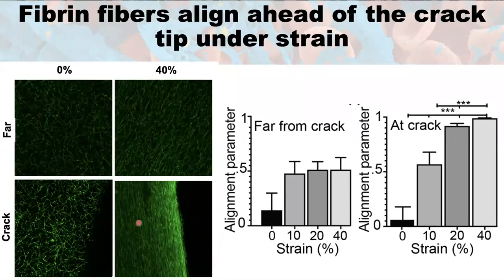And so first we saw that there is fiber alignment that happens in the region that is immediately ahead of the crack tip. So here you can see that in the area immediately ahead of the crack tip, we get increasing alignment, expressed as the order parameter, with increasing amounts of strain. This does not happen at the areas removed from the crack tip. We see that there is some degree of strain, but at the low levels of strain that we're looking at, we don't see alignment removed from the crack tip.